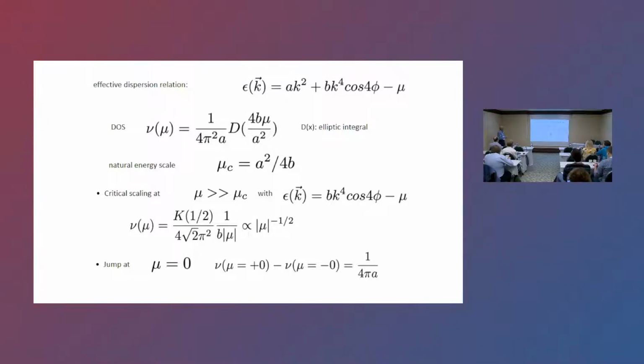Van Hove singularity. If you do it carefully, then the density of states as a function of the distance is proportional to an elliptic integral. We have natural energy scale a squared divided by 4b. And if we are at a distance away from the critical, which mu c 0 in our case, then effectively we see this dispersion relation with exactly the exponent that we like, and which translated will give us 1 over h minus hc dependence in the specific heat.